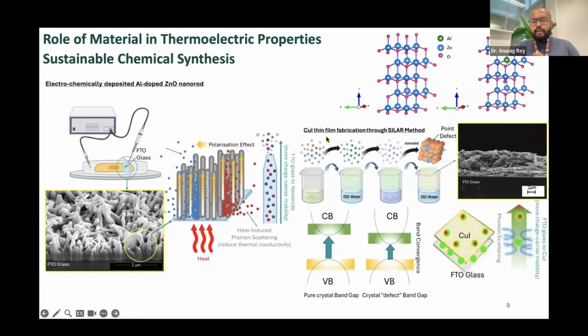The other thing is the copper iodide. So why are there two materials? The aluminium-doped zinc oxide works as an N-type electrode. If you remember the schematic of thermoelectricity, there is an N-type and a P-type. So N-type is the aluminium-doped zinc oxide, and on the other hand, the P-type is the copper iodide. The copper iodide thin film fabrication has been done through the SILAR method. It's a successive ionic layer adsorption reaction, SILAR is the full form.